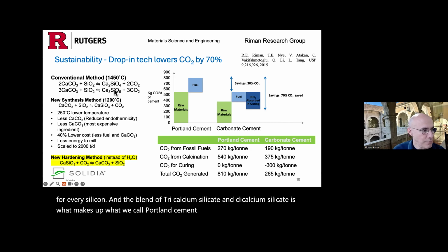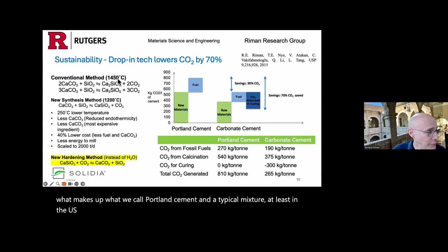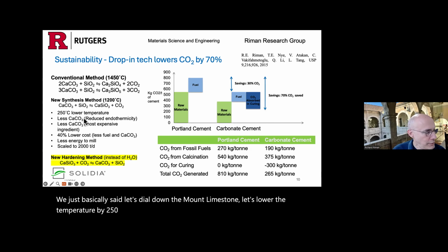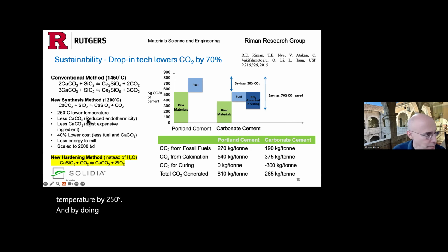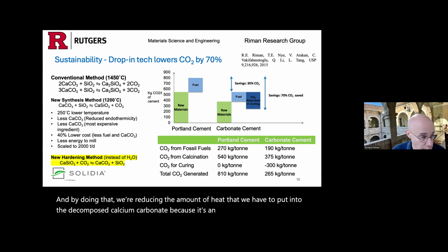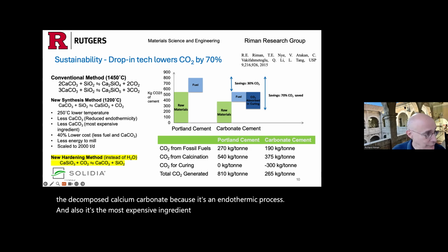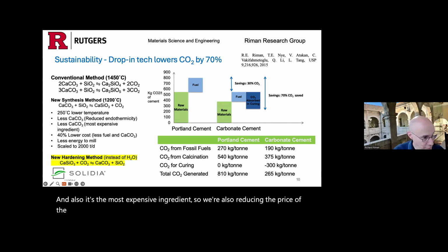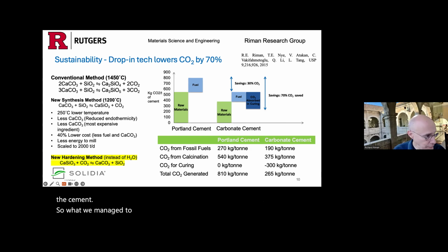And a typical mixture, at least in the US, is typically made at 1450, but it could be as high as 1600. We just basically said, let's dial down the amount of limestone. Let's lower the temperature by 250 degrees. And by doing that, we're reducing the amount of heat that we have to put into decomposing calcium carbonate because it's an endothermic process. And also, it's the most expensive ingredient. So we're also reducing the price of the cement. So what we managed to do with just these small changes is that we lowered the cost of cement by 40%.